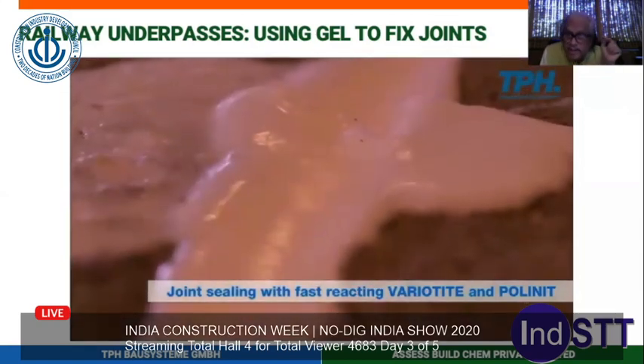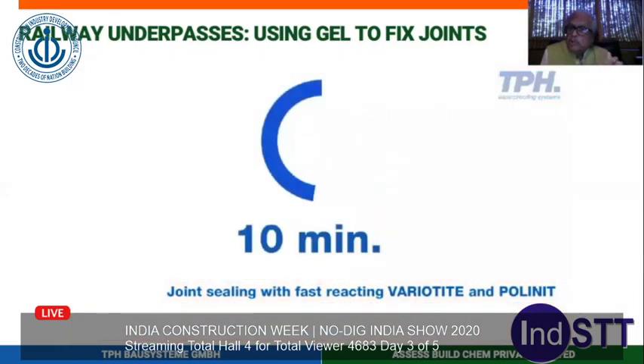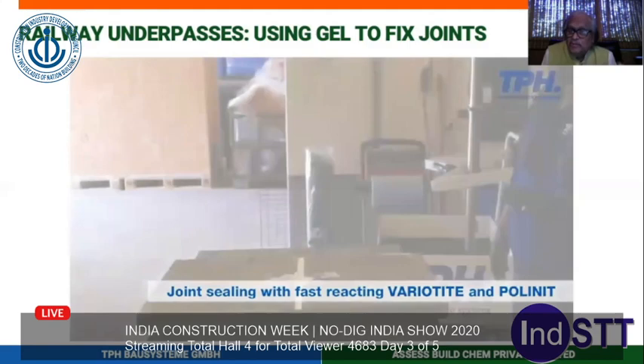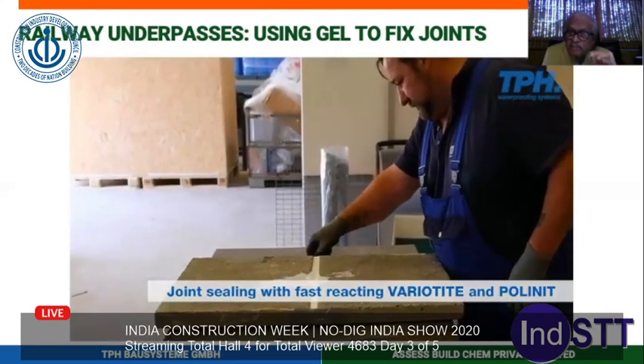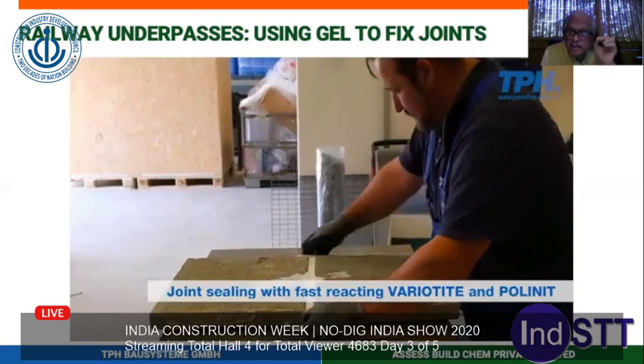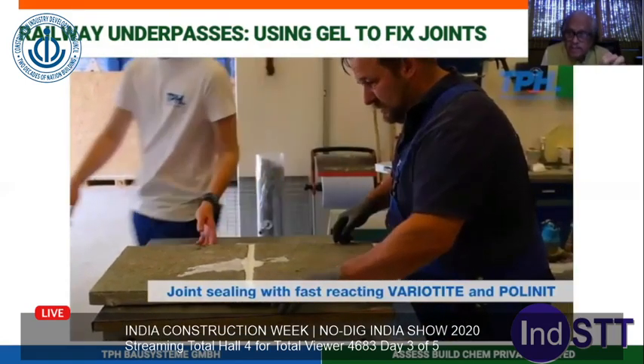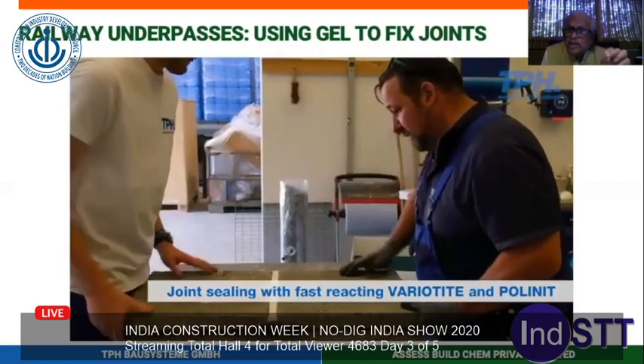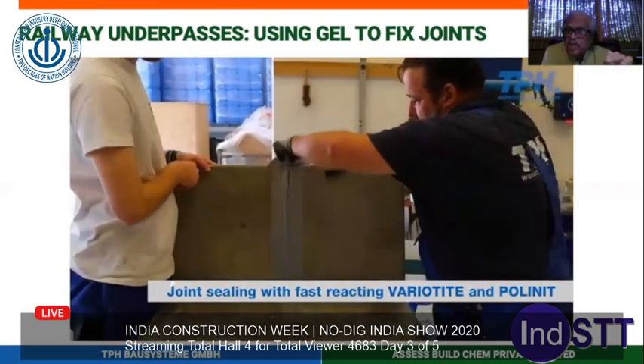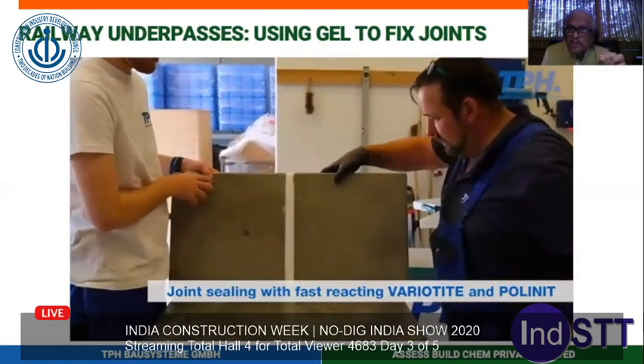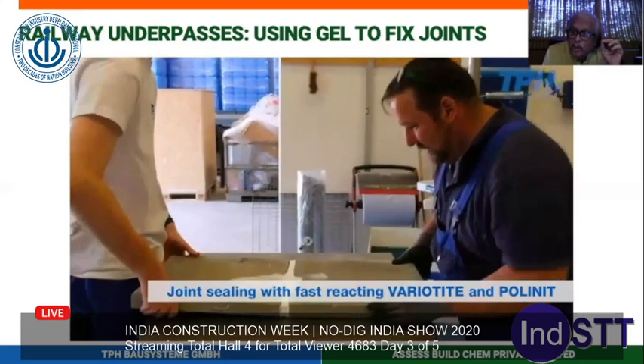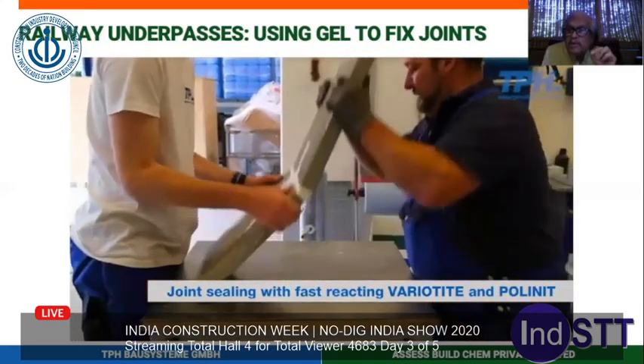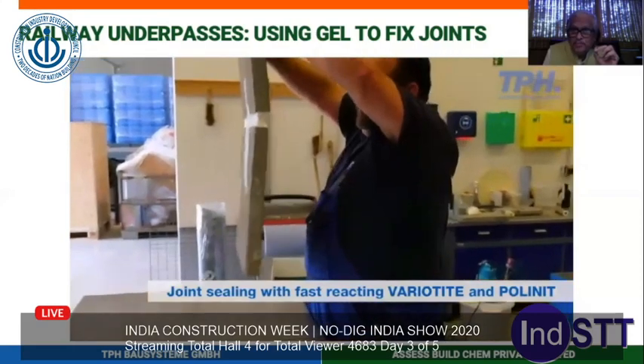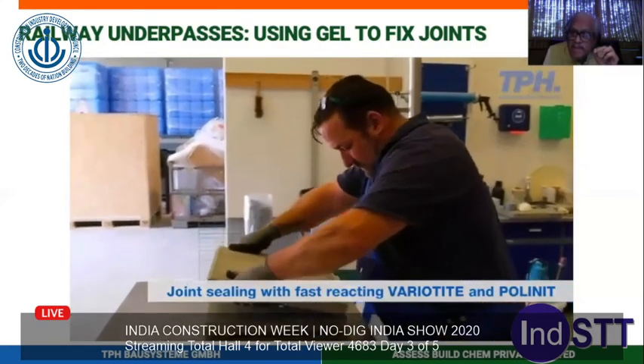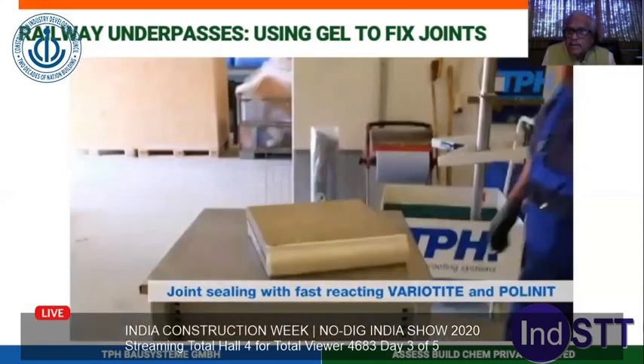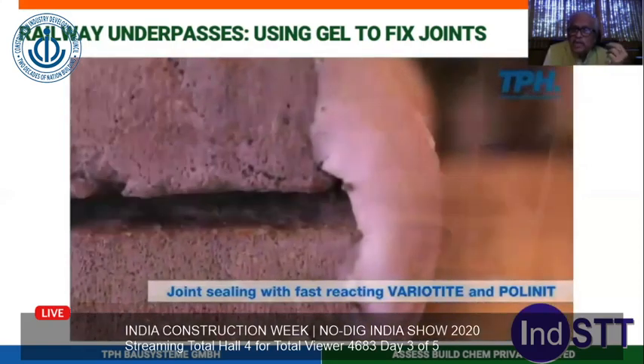If you tell me you put any other rigid polyurethane inside, you put a flexible polyurethane inside, within 10 minutes it has developed adequate bonding strength, which is most important. Any material you are using to recreate the joints in the segments or to recreate the joints for the underpasses or any other joint from where the water comes, a joint is a joint. It is to be treated like a joint. The bonding should be there on the sides and it should have enough elasticity. You can see here within 10 minutes. That means any water that is coming, it reacts with water and it is totally elastic.